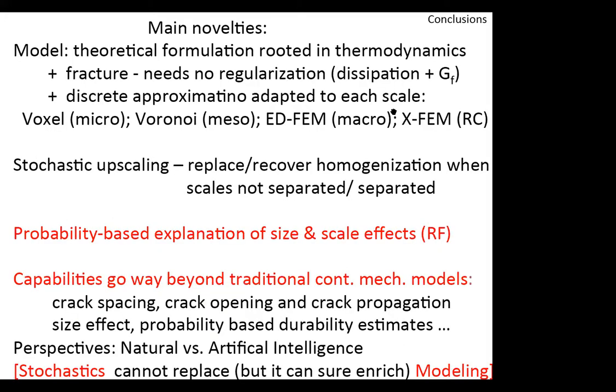First of all, what I really try to convey here is these different types of ingredients of the model for handling the fracture in terms of the size effect and the reduced model. So what I find the main novelties is, first of all, the theoretical formulation, which is very strongly rooted in thermodynamics. We just don't need any regularization, any intrinsic length or any type of viscosity or any type of trick like that. You simply need one of the most reliable parameters to identify, and this is your fracture energy.